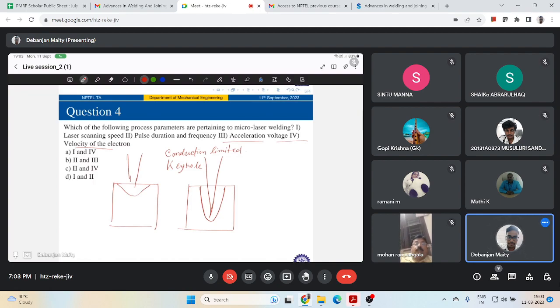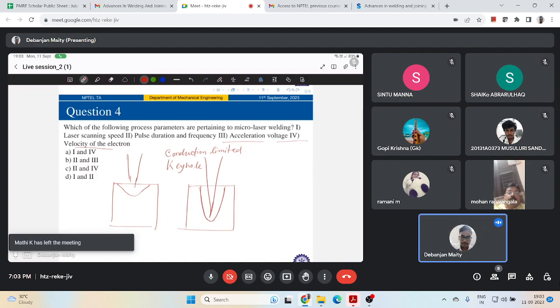Now, what is happening in keyhole? Here, molten metal starts to vaporize, and your power density can exceed something like 10 to the 6 watt per centimeter square. When you are doing this keyhole, it opens up a blind hole in the molten metal, and the vapor pressure from that hot metal keeps the hole open during the weld, right? And it increases the energy efficiency of this welding process, because with this penetration depth you can have multiple reflections of the beam within the cavity, like this, right?